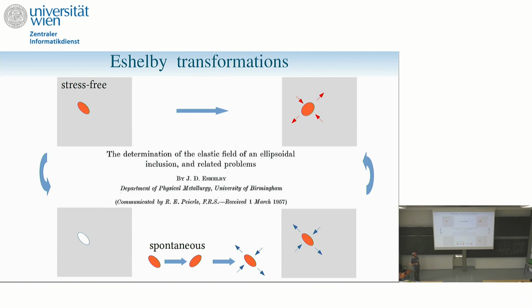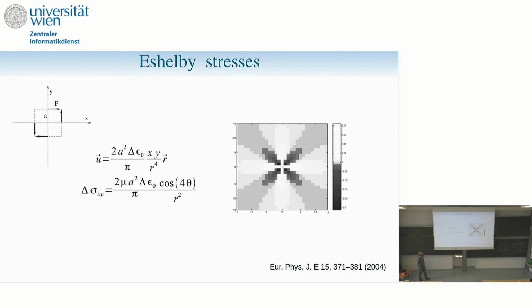And so the argument is, when this happens, you exert these forces to fit it back in, and now you just let go. And it turns out that the result amounts to adding some set of forces. It's the elastic response of the system to forces on the edge of this inclusion. Okay? So you can calculate this. This is some paper by Picard and others.